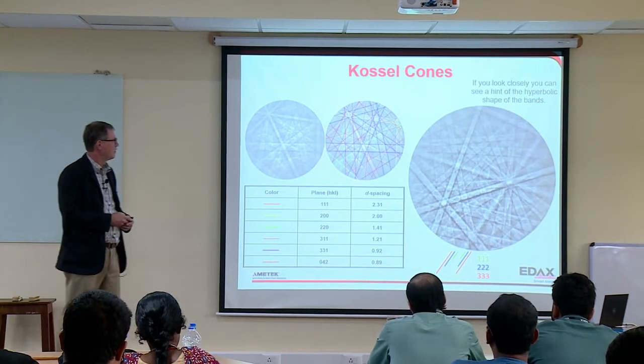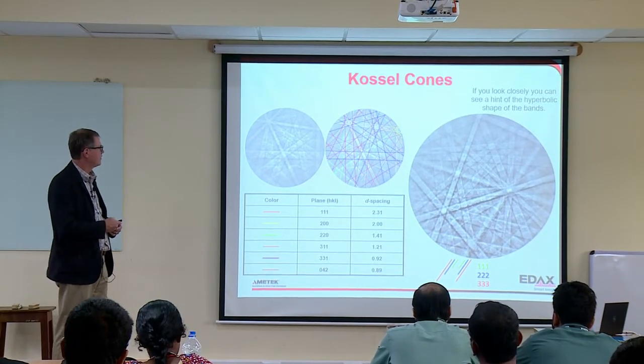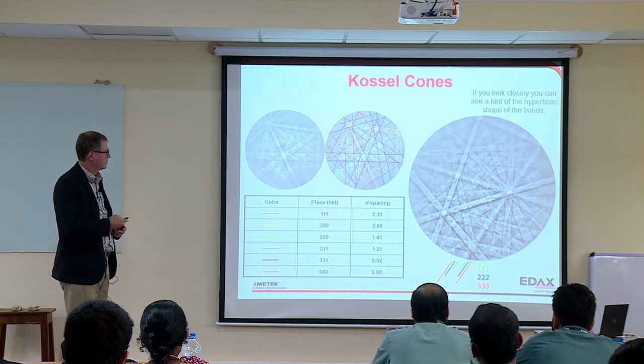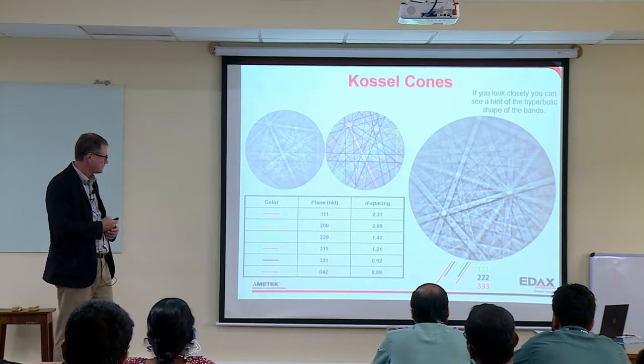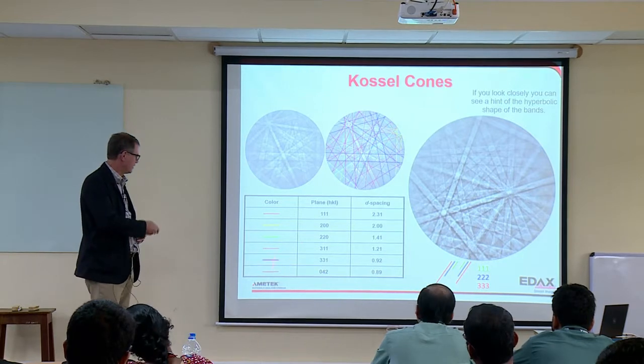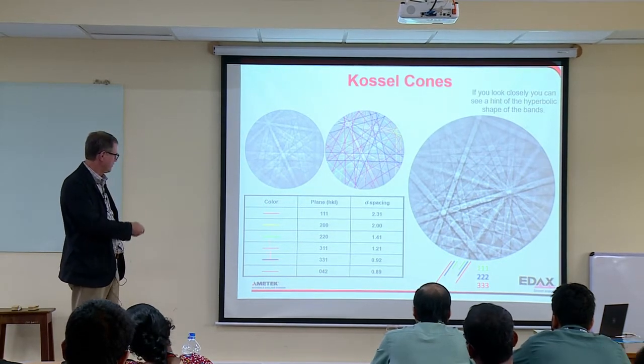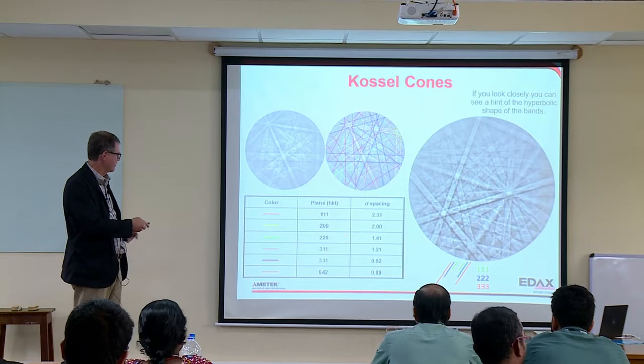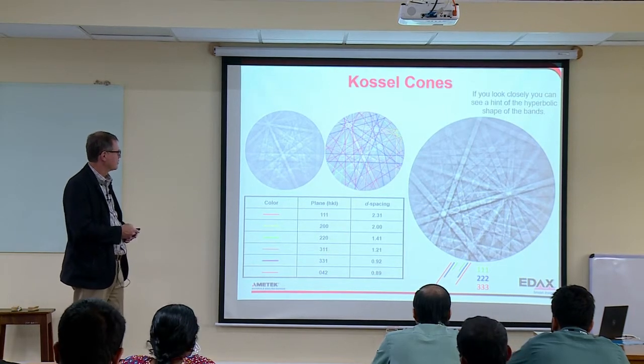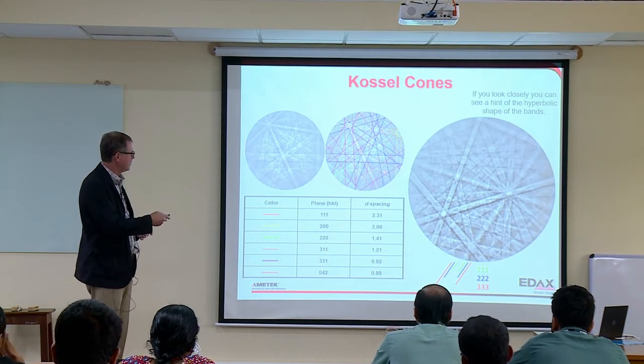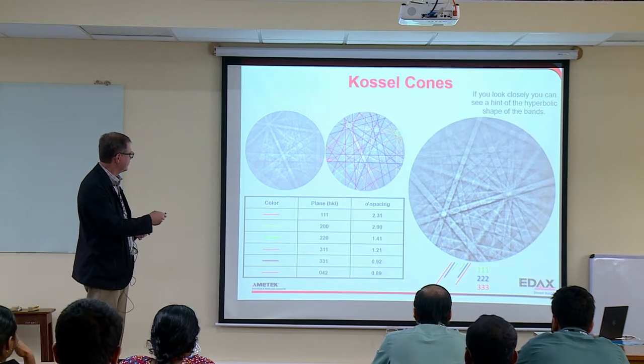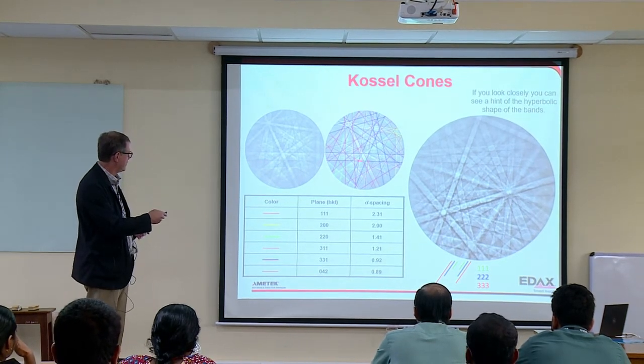As an example here, this is a very nice pattern from silicon. And these are the different, some of these are the reflectors in our material, and I've just assigned them colors, just randomly. But if you look really, really close, for example, this band here, you can see there's a slight curvature of that blue line.